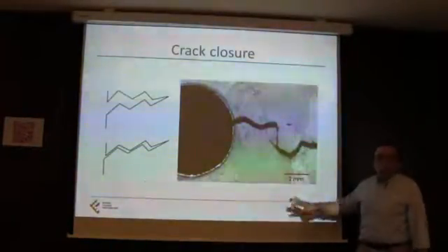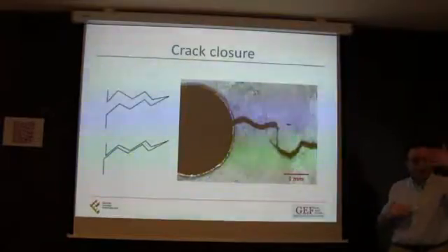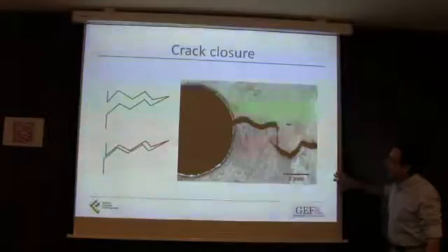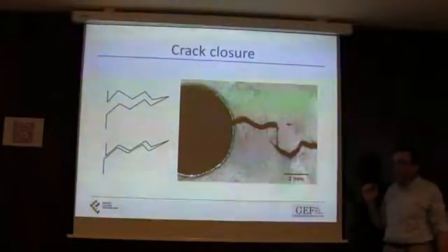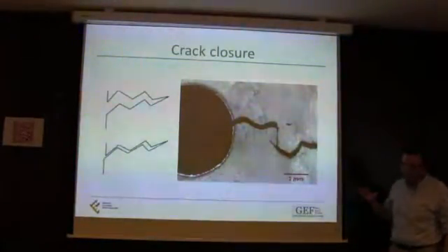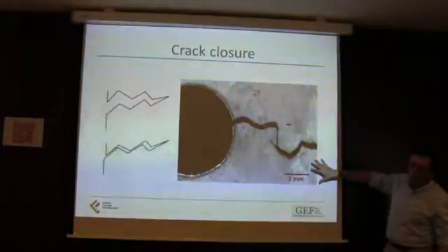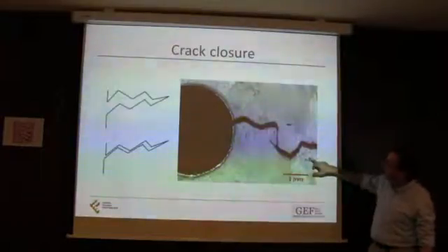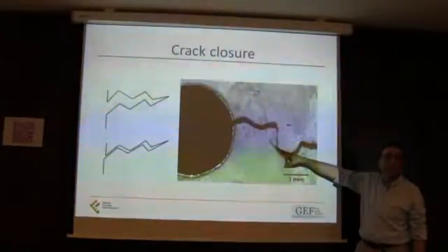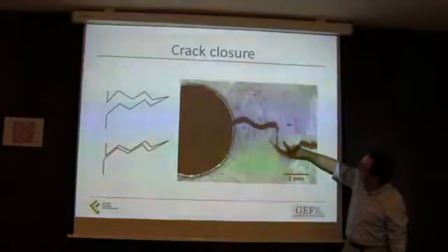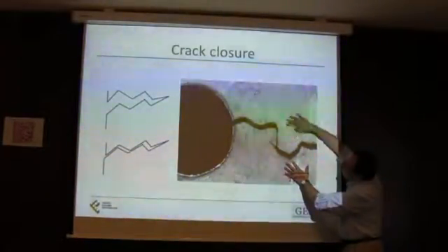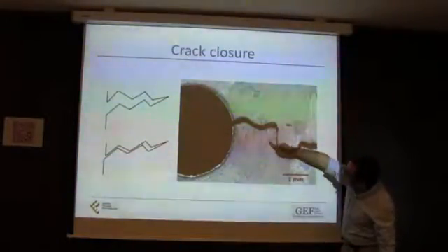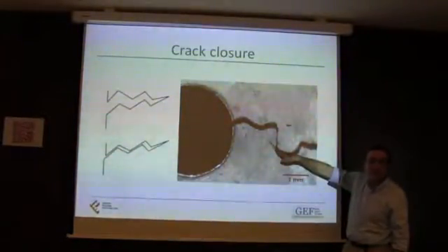Well, you have all sorts of very complicated behavior. Jaroslav was talking about crack closure before. I think you said that you don't expect much crack closure in short cracks. Well, it's the other way around, I think. You can see that here. The crack morphology is so complicated that you have this very striking example of crack closure. This thing here is impeding the upper part from going up, and it exerts some force here that has actually initiated this secondary crack here.